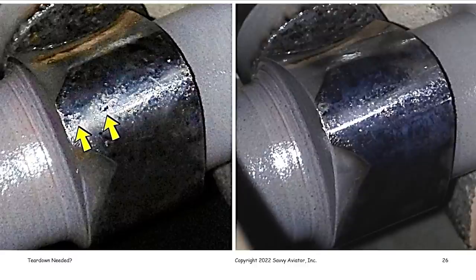So basically the cam is made out of tough material, but it has this very hard outer layer that provides a good wear surface. And as long as you haven't penetrated that outer layer, that 15 thousandths or so thick carburized outer layer, the cam's okay. It may have some minor surface issues, but it's okay. But once you penetrate that 15 thousandths hardened layer and get into the softer inside meat of the cam lobe, the wear will start to accelerate very, very rapidly, and it will start throwing off metal, and you'll see metal in the oil filter and stuff, and that's when the cam is unairworthy.